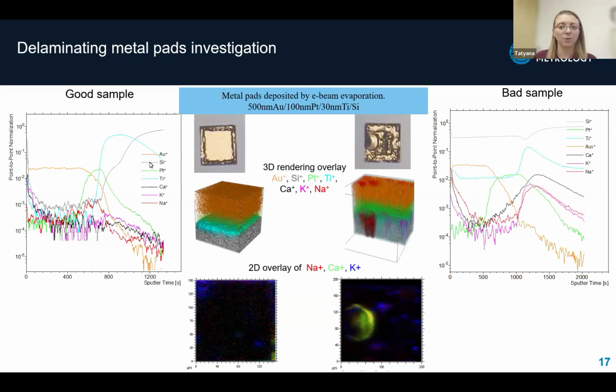This analysis shows that delamination issues can be directly linked to both structural integrity and contamination in the metal layers. Understanding these failure modes is crucial for improving the deposition process and ensuring quality control.